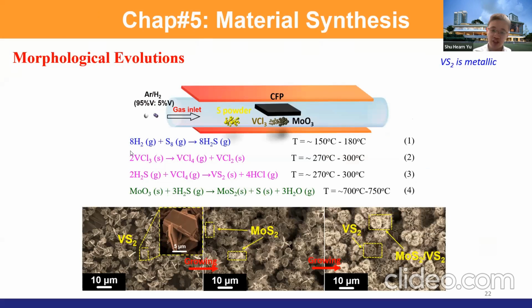I basically try to exploit the evaporation temperature of our precursors. Sulfur will react with hydrogen at about 180 degrees. And this is vanadium chloride. Vanadium chloride will evaporate at around 300 degrees C. And then molybdenum oxide, the evaporation temperature will be higher, 750 degrees C.